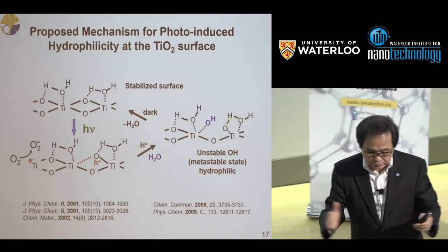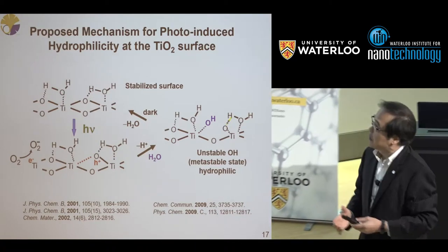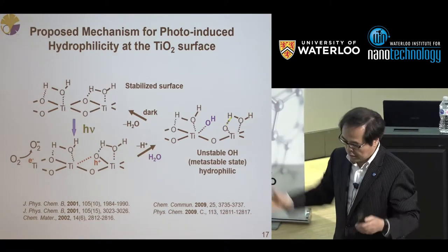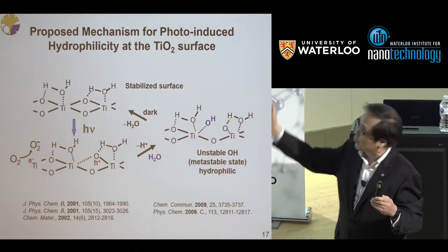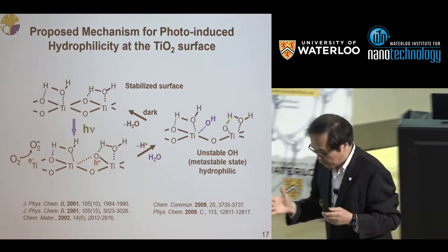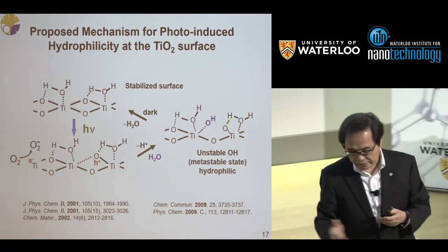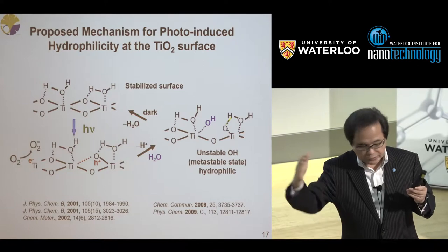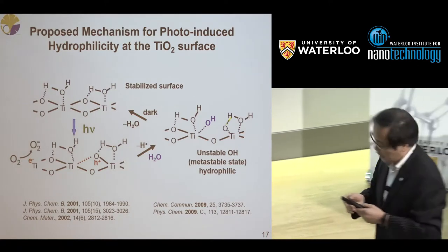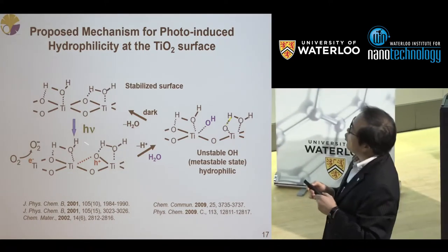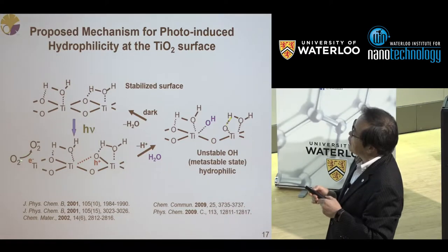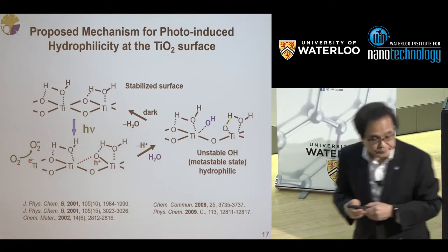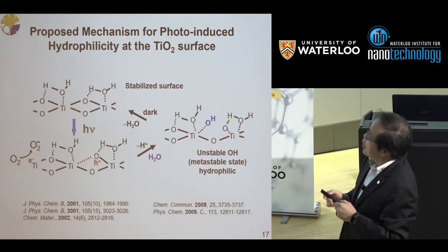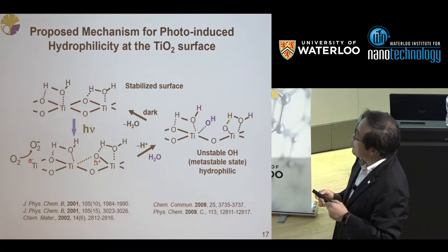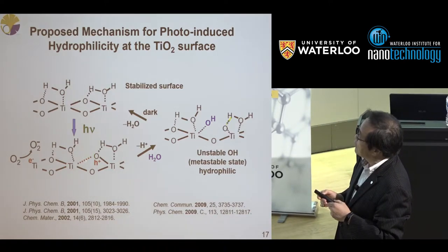I don't explain the details, so only our conclusion is shown here. Based on the various experimental data, we proposed this mechanism. The light illumination creates electrons and holes, and the electron is consumed by reacting with oxygen. Then the hole decomposes titanium dioxide itself.